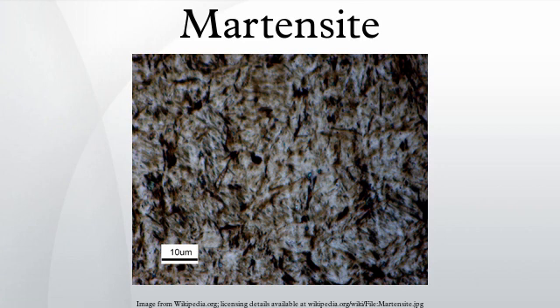For steel with 0 to 0.6 percent carbon, the martensite has the appearance of lath and is called lath martensite. For steel greater than 1 percent carbon, it will form a plate-like structure called plate martensite. Between those two percentages, the physical appearance of the grains is a mix of the two.